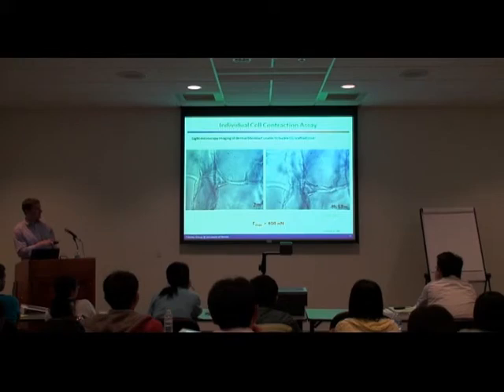And what we watched it do over the next couple hours is round up, and then it started to elongate again, and it again generated this nice high aspect ratio structure, and very, very soon after, it broke again. And so what we could watch is an individual cell inside this 3D scaffold structure attempting to contract a fiber, but not actually being able to generate enough force. But because we were able to measure the local geometry of the strut structures, we could actually make a calculation of how much force it would have taken to buckle that strut region. And this one worked out to be about 450 nanonewtons.